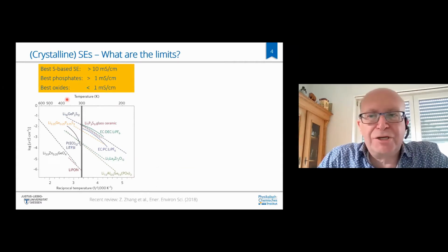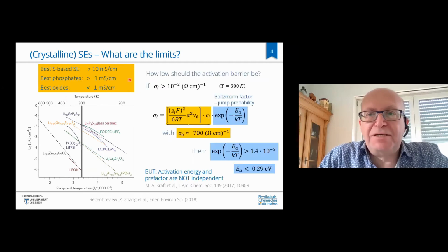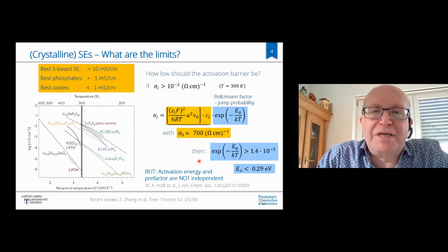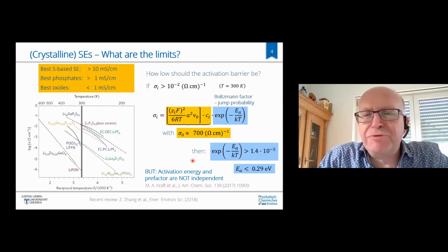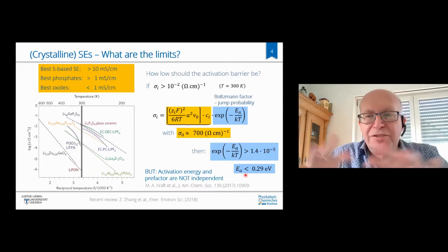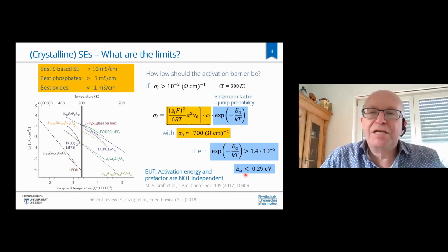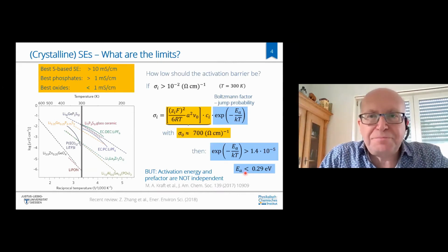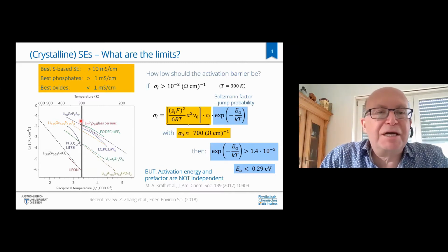a few minutes to really show the problem. We really need these very high conductivities of the sulfides and thiophosphates. And if you make a simple kinetic analysis of what we can get with solid electrolytes, then of course there is no serious limitation to approach these high conductivities. What you need is a low activation energy, a high concentration of lithium ions in the structure, and a reasonable transport path in the structure. But then it's no problem to approach these 10 millisiemens per centimeter at room temperature for activation energies roughly below 0.3 eV. And with the thiophosphates, where lots of work has been done by our Japanese colleagues in the last 1 or 2 decades, the thiophosphates can meet that.